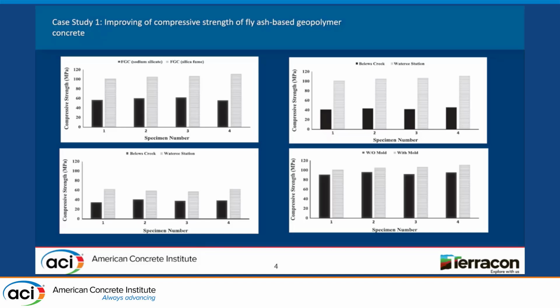And also here we didn't use any water for curing or water with lime. So it also has a good advantage that we don't need to waste water to keep the curing going. After we subject it to external heat, after 24 hours we will be good to go. And I believe this concrete is good also, especially without the need for mold.